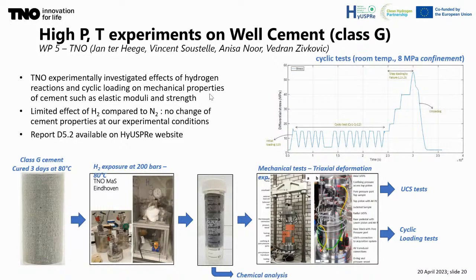And what you see is the stress evolution. And what we found, confirming earlier work reported, is that there is a limited effect of hydrogen compared to nitrogen. So no change of cement properties at our experimental conditions is basically the result. So this appears to not be the greatest concern, the impact of hydrogen exposure on cements.